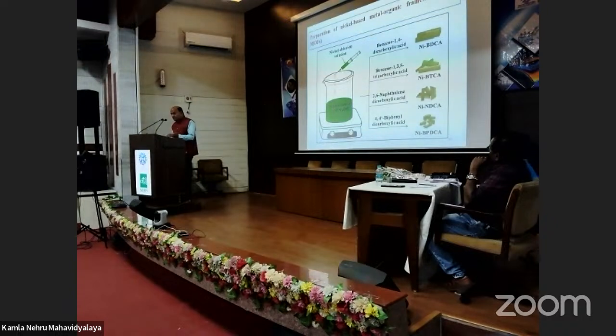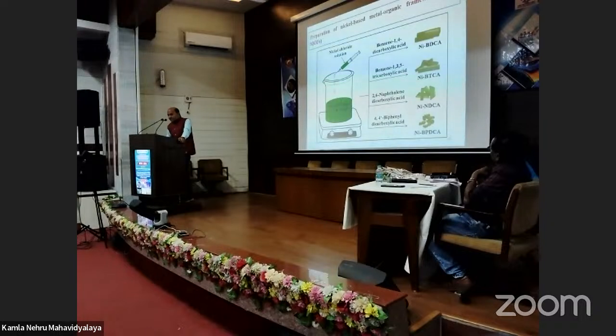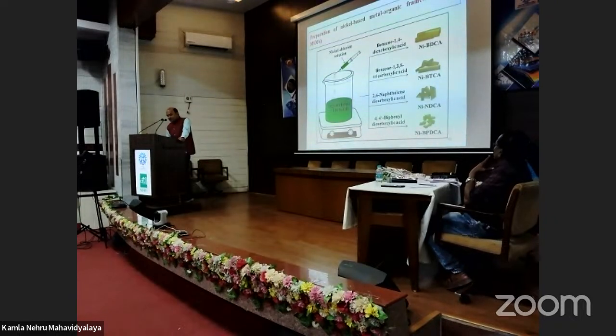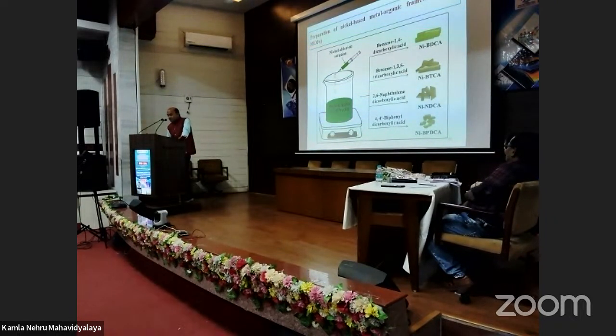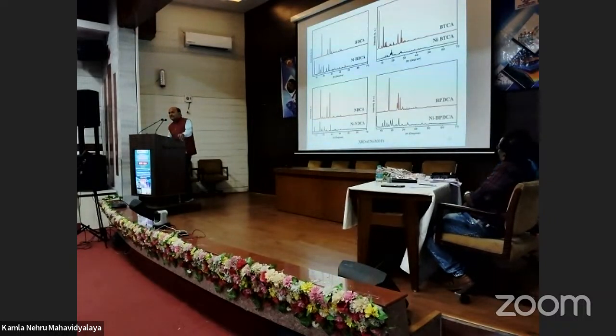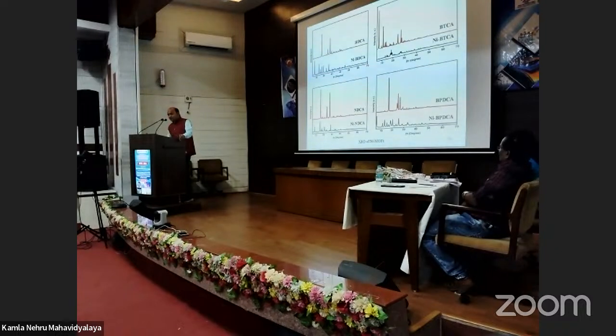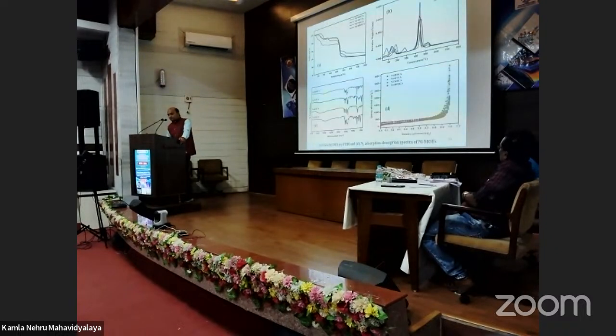I will go fast. Preparation of the nickel MOF. This is the way we have used 4 organic linkers: benzene 1,4-dicarboxylic acid, benzene 1,3,5-tricarboxylic acid, 2,6-naphthalene dicarboxylic acid, and 4,4-biphenyl dicarboxylic acid. We have named them NiBDCA, NiBTCA, NiNDCA, NiBPDCA. So these are the exciting things compared with that particular organic linker. Thermal stability with UV DRS and XRD we have done.